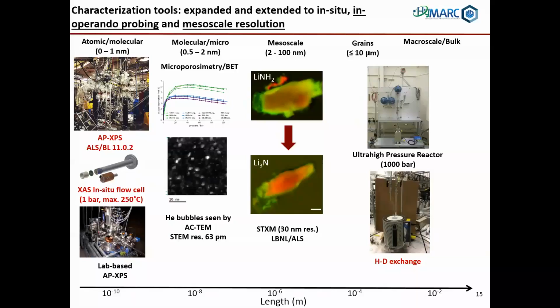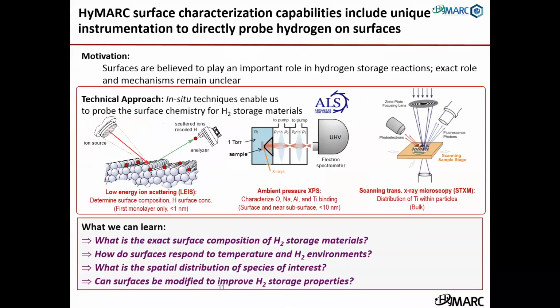Next slide. An example of where we have particularly deep capabilities is in the area of surface chemistry. Of course, hydrogen has to interact with the surface of any storage material. That's the first thing it does. But there's a misconception that some widely used analytical tools, like X-ray photoelectron spectroscopy, are able to actually detect hydrogen at the monolayer surface. That is actually not correct. XPS is probing several nanometers into the bulk. So HyMARC has access to an instrument at Sandia called low energy ion scattering, and this tool can look at the atomic monolayer and can detect hydrogen specifically. It's the only diagnostic tool that is capable of doing that.